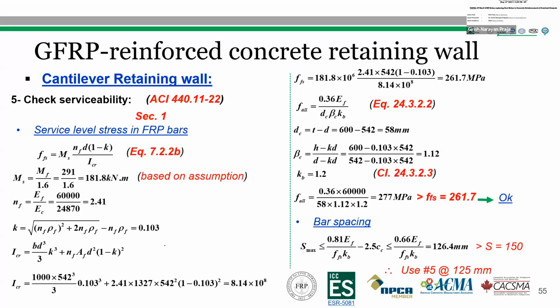So for section 1 of the retaining wall, the service level stress was around 261 megapascal, which should be lower than the GFRP stress calculated using this equation, the equation in 24.3.2.2. In this case, DC is the effective depth, 58 millimeter, and beta C is a coefficient which is equal to 1.12, and the value here is 277 megapascal, which is greater than the service level stress in the FRP bar.